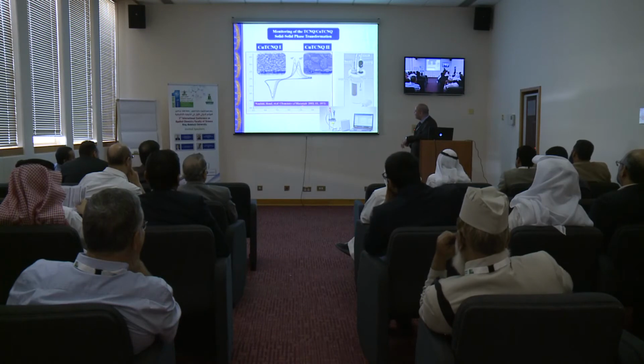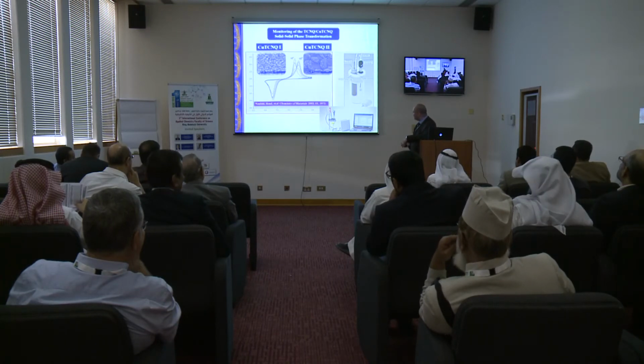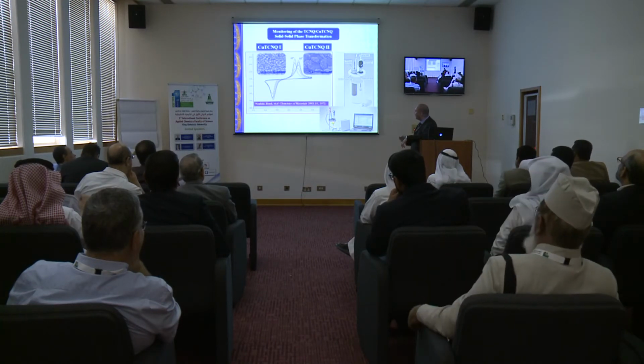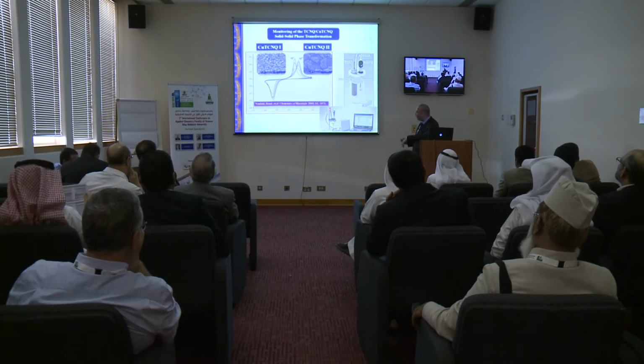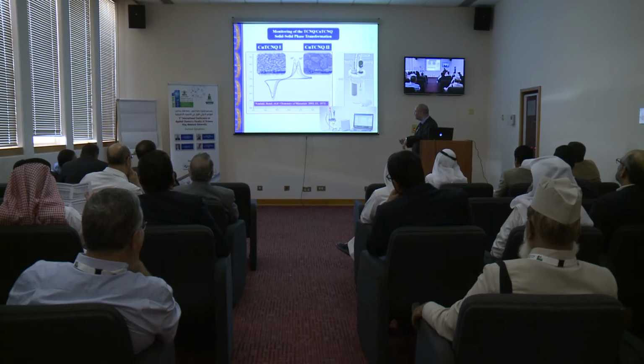Simply, what we do is we scan, applying a potential through this potentiostat to the cell, which would contain, at this time, if you have copper, let's say, a copper sulfate solution. As we apply the potential, we get to a point where we can reduce TCNQ by one electron to make TCNQ minus, and now it's in the solid phase. And as a result of forming TCNQ minus, for charge neutralization, copper has to migrate from the solution into the crystal lattice to form copper TCNQ.